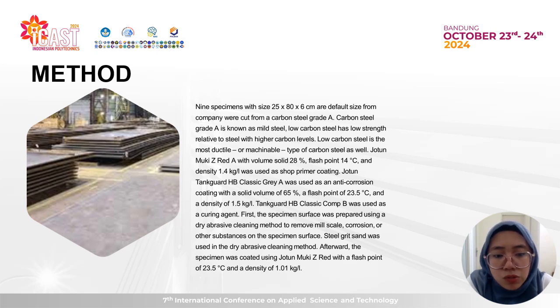First, the specimen surface was prepared using a dry abrasive cleaning method to remove mill scale, corrosion, or other substances on the specimen surface. Steel grit sand was used in the dry abrasive cleaning method. Afterward, the specimen was coated using Jotun Muki Z Red A with a flash point of 23.5 Celsius.